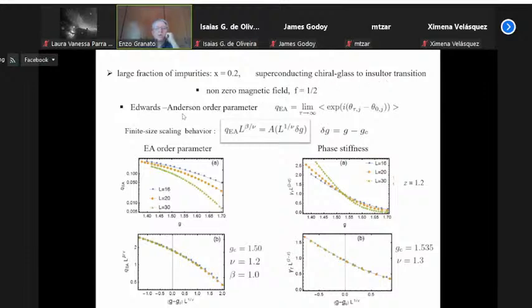The appropriate quantity to look at is the Edwards-Anderson order parameter, and this is illustrated here. The finite size scaling used to describe the data is written here. From that, you can get the critical exponent. You can also look at the phase stiffness, which is a measure of the superconductor-to-insulator transition. From that, you find that there is a chiral glass to insulator transition, and there is a superconductor to insulator transition. And the critical couplings for both the chiral glass and the superconductor-to-insulator transition are very close together, actually within the error bar. So the chiral glass-insulator and the superconductor-insulator transitions happen either at the same temperature or at temperatures very close together.